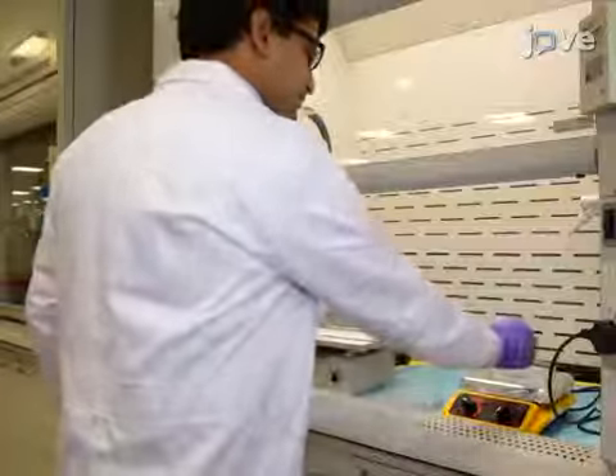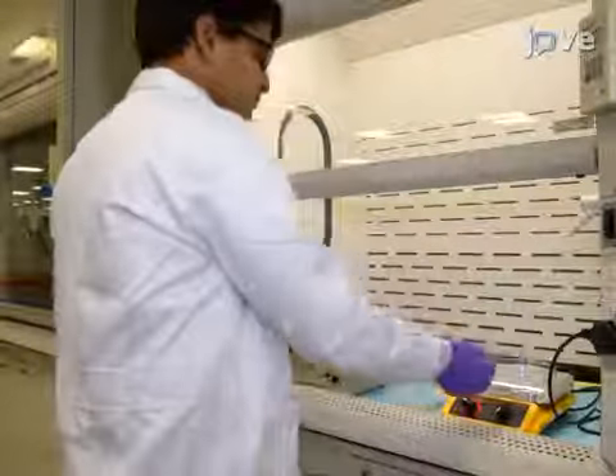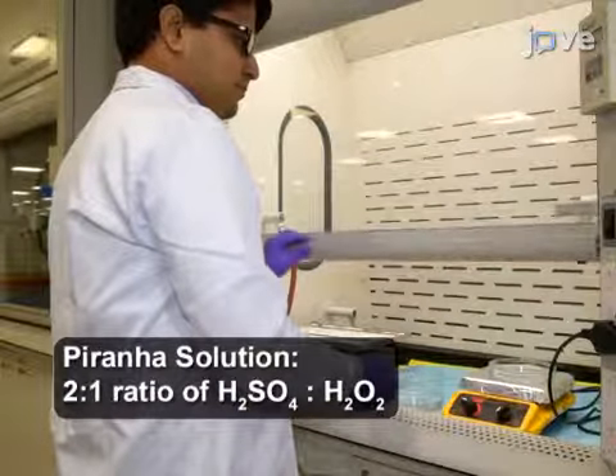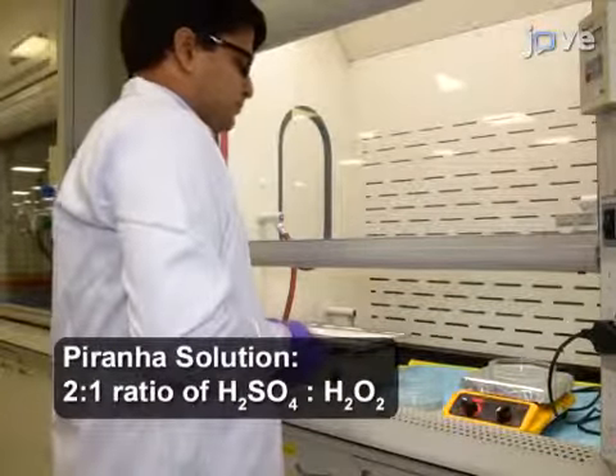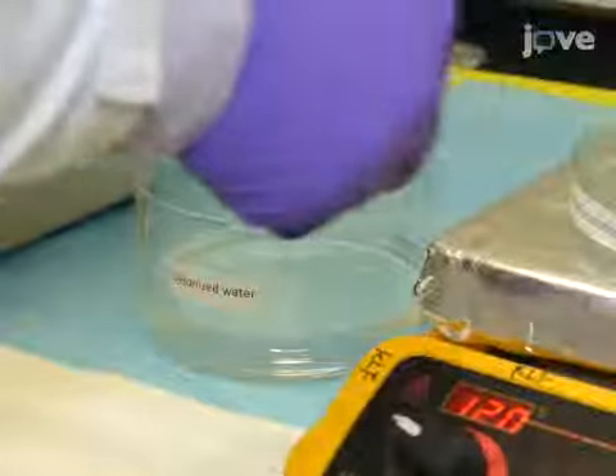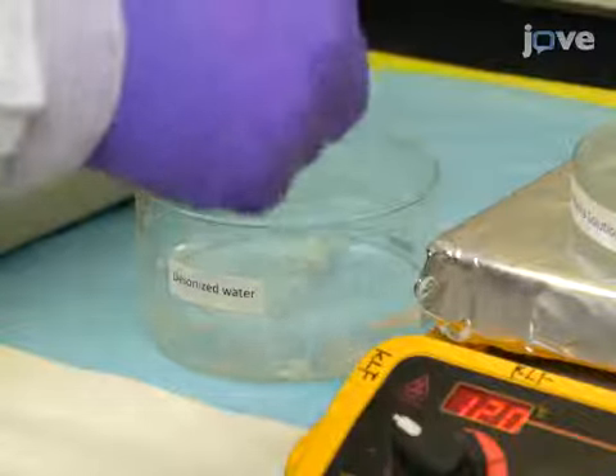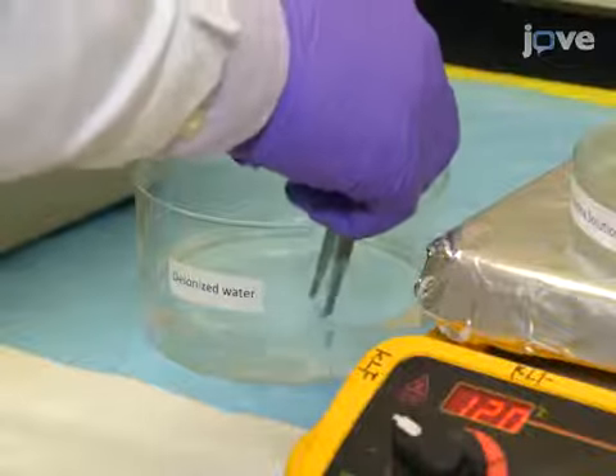Begin cleaning a 4-inch glass wafer by immersing it into a quartz tank filled with piranha solution for 20 minutes at 120 degrees Celsius. Then rinse the wafer in distilled water and dry it using compressed air.